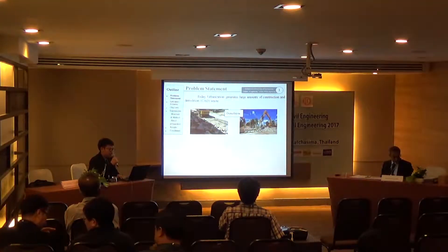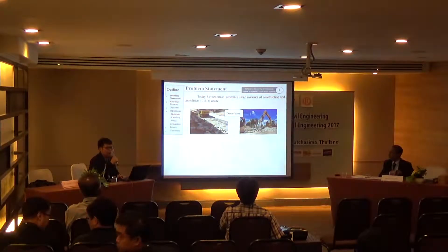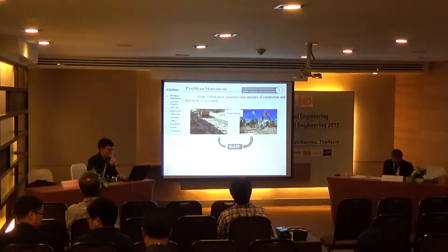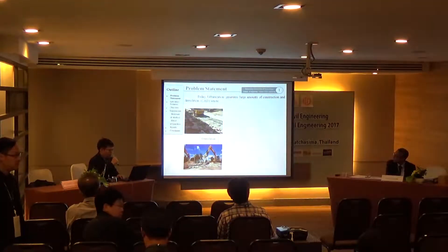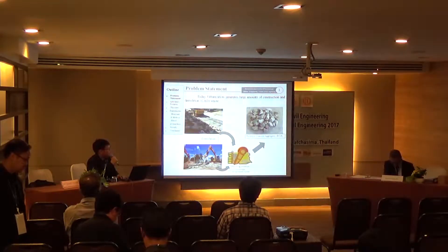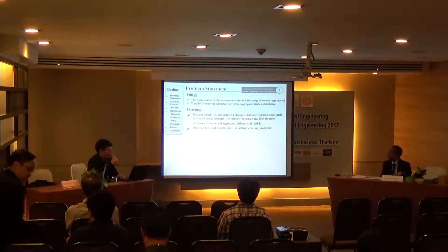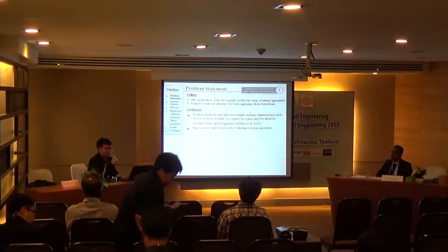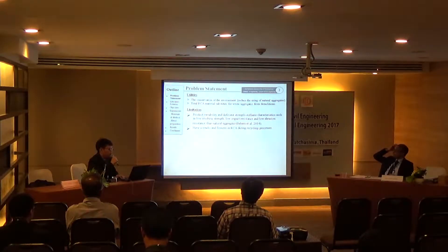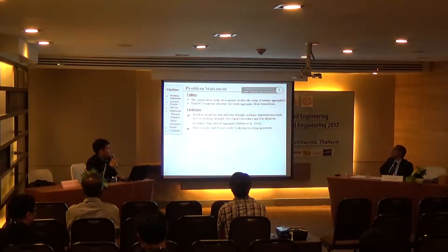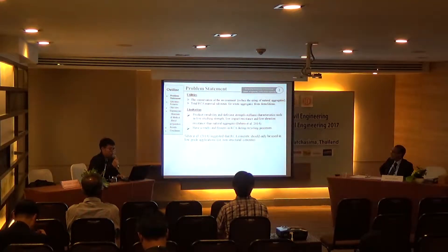Today, the background section covers large-scale construction and demolition waste in the form of recycled concrete aggregates, which are obtained from the demolition of concrete buildings. Normally, it is a material used for backfilling, but recycled concrete aggregates can be prepared by using crushing and screening processes to be used in concrete production. The use of recycled concrete aggregates helps preserve natural aggregate sources. Some limitations include low tensile strength, lower bonding, and lower density compared to natural aggregate, and also cracks from the recycled concrete process. Therefore, concrete made from RCA should only be used in local applications such as concrete roads, concrete canals, and breakwaters.